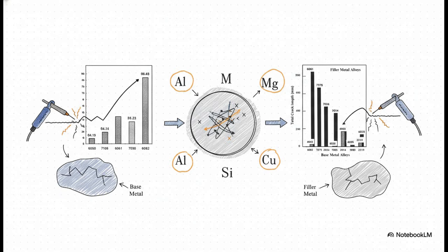Now, don't worry about every detail on these charts. They're showing results from tests for solidification cracking. The main takeaway here is that for both processes, this is a real danger. It all comes down to choosing the right filler metal for your base metal to control the chemistry and prevent those tiny cracks from forming as the weld cools.